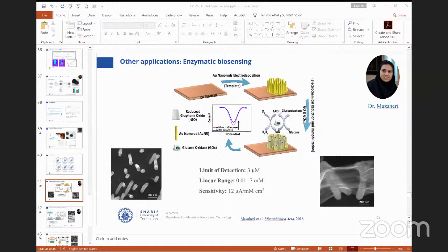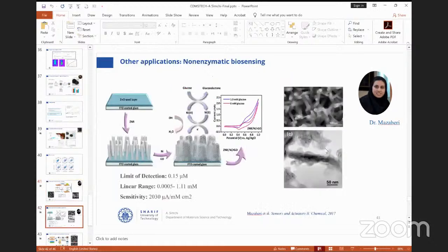However, there is a lot of interest in non-enzymatic biosensing. For this purpose, we also developed another biosensor based on zinc oxide nanorods, and then we conformally coated the nanorods with graphene oxide nanosheets.